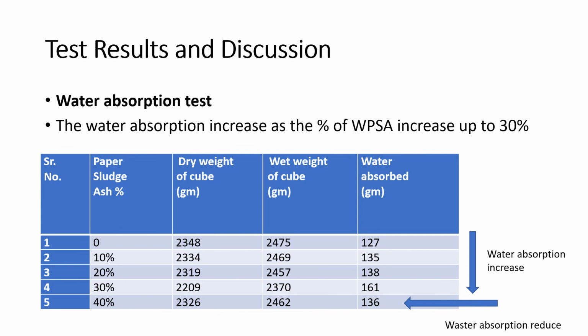In terms of the water absorption test, the results indicate that the water absorption increases as the percentage of the waste paper ash increases, but that is only up to 30%. When we increase more than 30%, then the water absorption basically reduces.